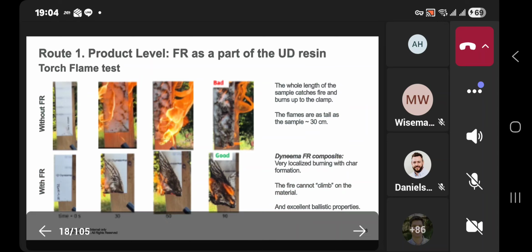So now I will show you some examples of what we have seen. You see here the results of adding a flame retardant within the resin, so at product level. This is a very harsh test we did, a so-called torch flame test. And you have there a sequence of pictures as a function of the testing time for two types of materials, without and with flame retardant. Without flame retardant is at the top, and you see that as soon as the torch flame makes contact, the composite catches fire quickly, burns with very tall flames, and it simply burns to the clamp. This is very bad, and you see that the material is melting and dripping, etc. All those things we don't want to see, and customers don't want to see.